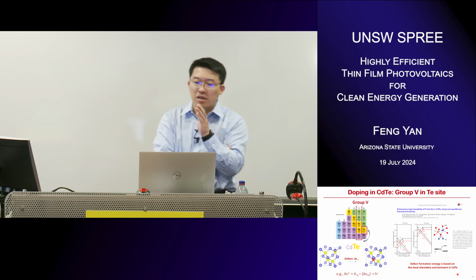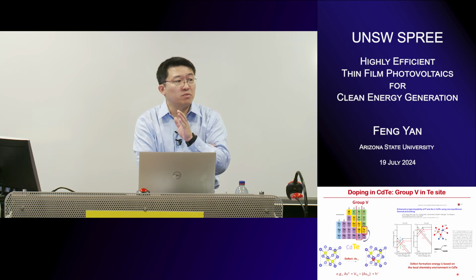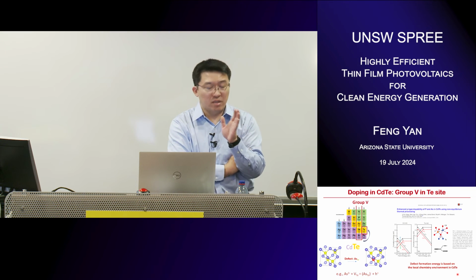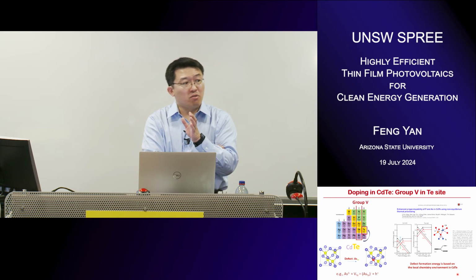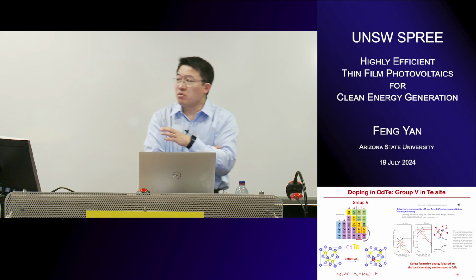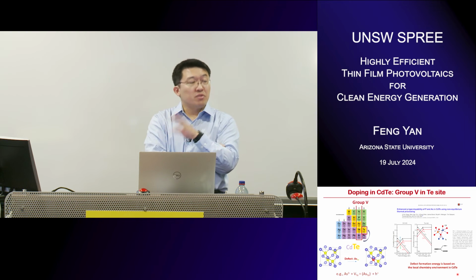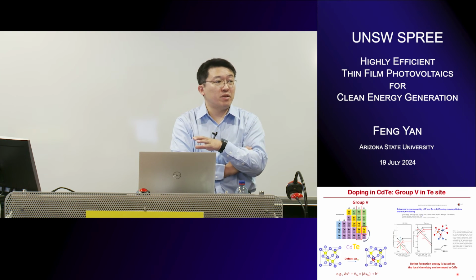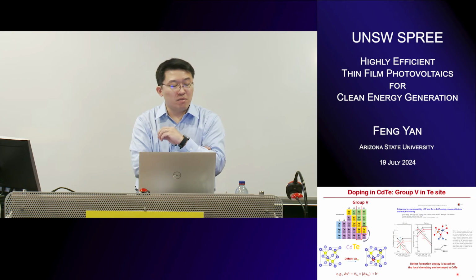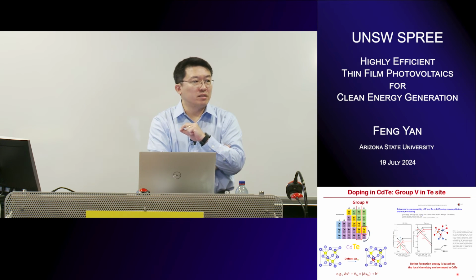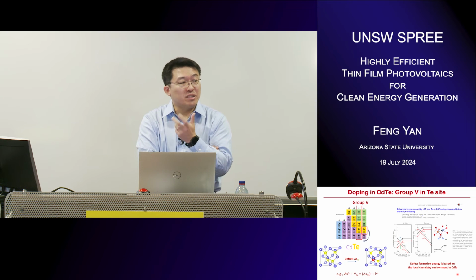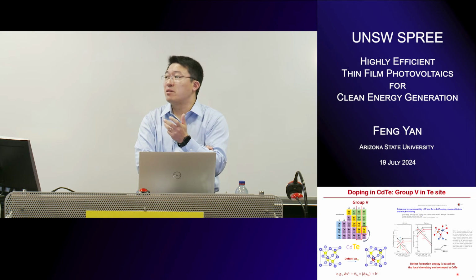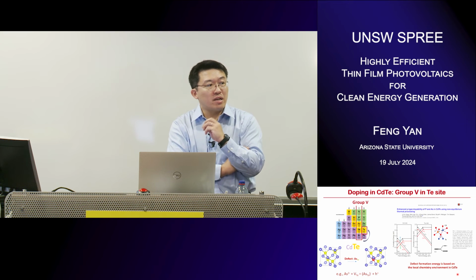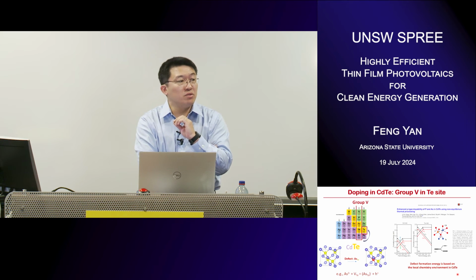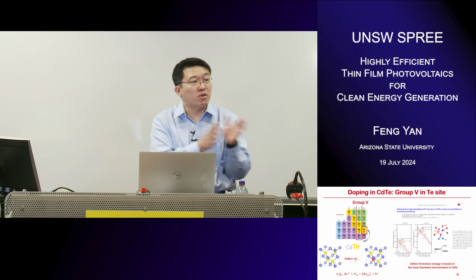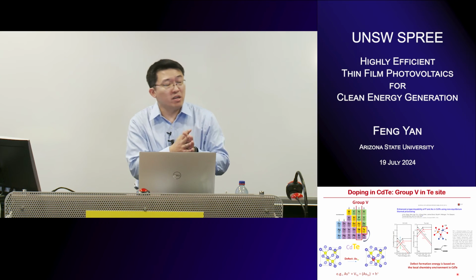Why? Because of the previous cadmium chloride step, for example, that's the activation process. We run it at around 400 degrees C. So we do not want to go over that temperature and damage the cadmium chloride treated film. That's why for antimony and bismuth, the temperature may be close to 400, but there is some risk of damaging the previously treated film. For phosphorus or arsenic, it can be controlled lower than or close to 300, so that gives us a temperature gap to protect the previous process.